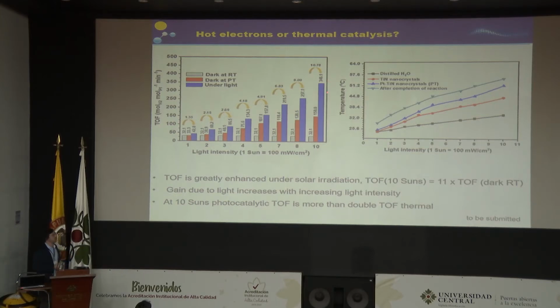Indeed, if we measure the temperature when we shine 1, 2, 3, up to 10 suns, we can vary the temperature of the reactors from, let's say, 25 degrees to almost 50 degrees. Of course at 50 degrees the reaction would go much faster. So we did a series of blank experiments at the so-called plasmonic temperature, but without shining the light. Basically, with this method, we were able to distinguish between the contribution due to the thermal effect of plasmons and the hot electrons, which come if you subtract this contribution from the big contribution.